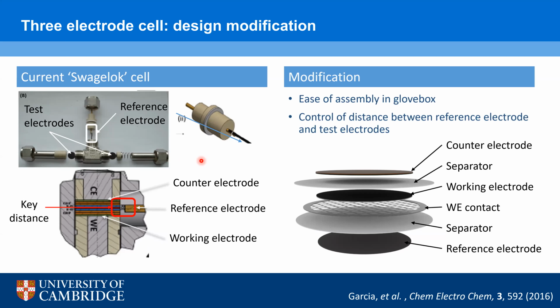Dylan mentioned reproducibility, and in terms of applying a reproducible amount of pressure when testing different cells. In this type of design, the 2 plungers are effectively tightened in opposition to each other, so it's quite difficult to control the amount of pressure that's applied to the cell. The reference electrode in this design is introduced in the middle through a kind of probe-like wire, and it has a small piece of lithium attached to the end at a fixed distance from the rest of the cell, which is being tested. So the things that we'd like to change and improve on this design are trying to make it as easy as possible to assemble within the glove box,